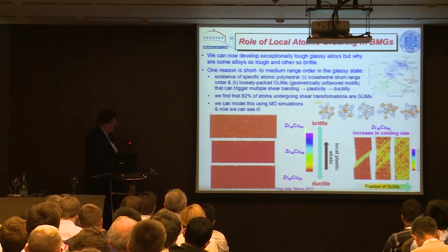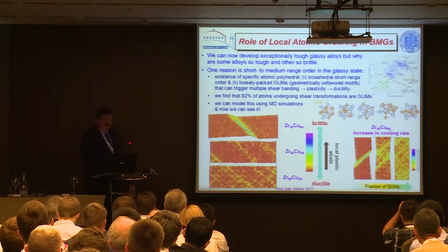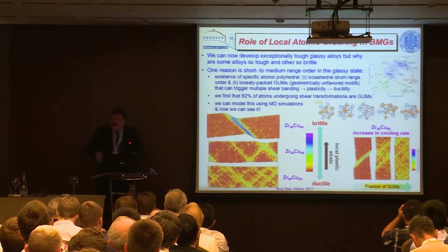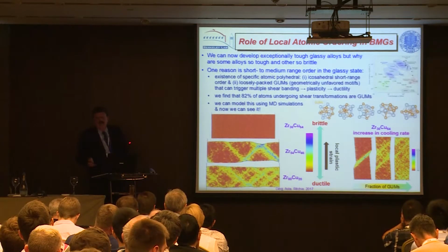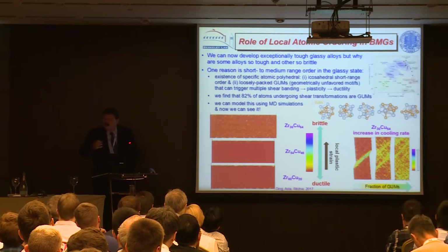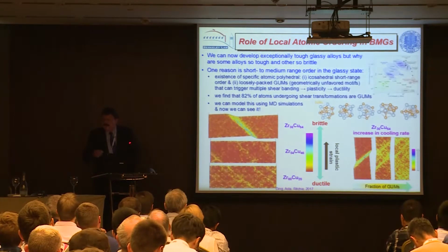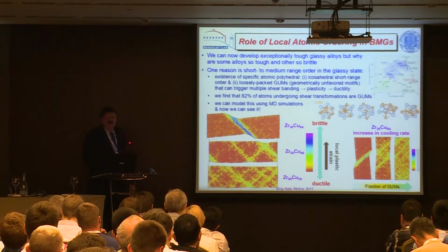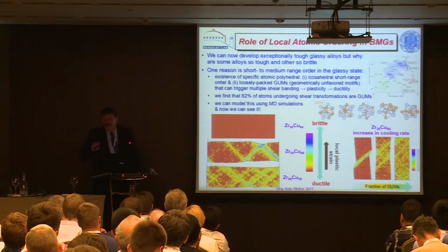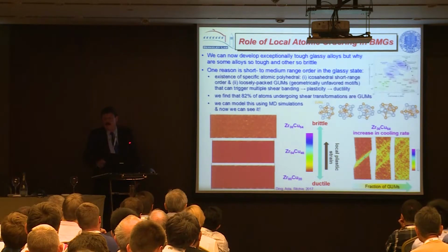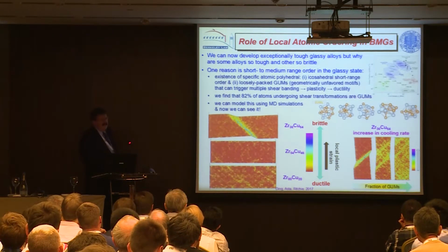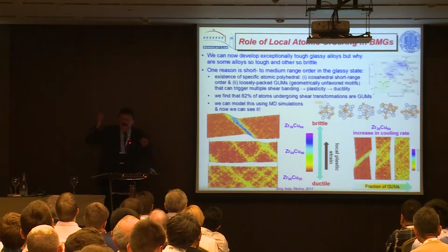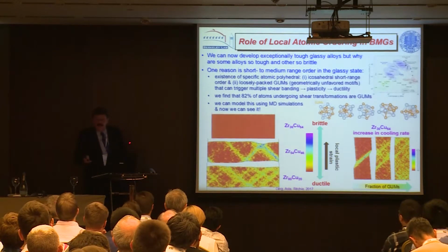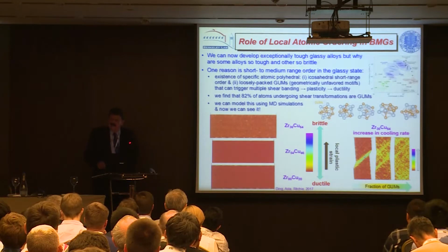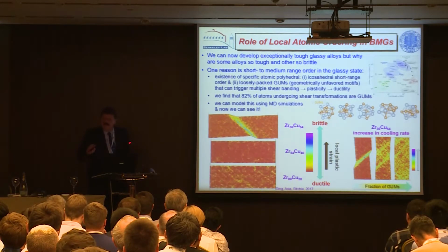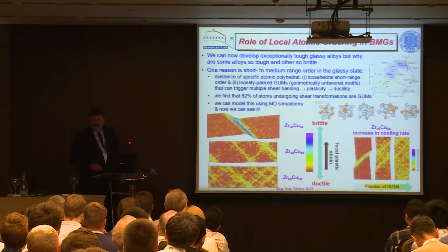And these things can be changed by composition. You can change them by increasing the cooling rate. The higher the cooling rate, the more likely you are to get these unstable local symmetry regions, which can trigger shear bands. So it's a very nice theory, but it's a theory. How do you experimentally prove this? An MD calculation or DFT calculation is at some ridiculously low temperature and very high strain rate. It doesn't necessarily appeal directly to reality. So can we actually see this, can we prove this experimentally?